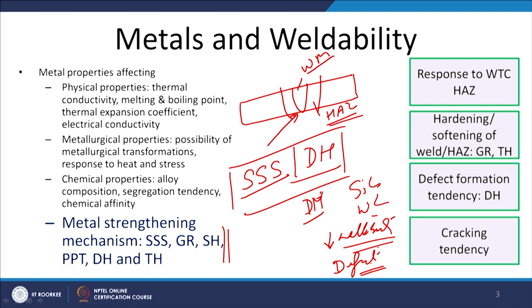state joining process. Since solid solution strengthening is due to the alloying elements, which by and large remain intact unless there is a huge loss of the alloying elements from the weld metal, properties are not significantly affected in the weld metal as well as the heat affected zone. But in case of the dispersion hardened materials, there will be a defect formation tendency.